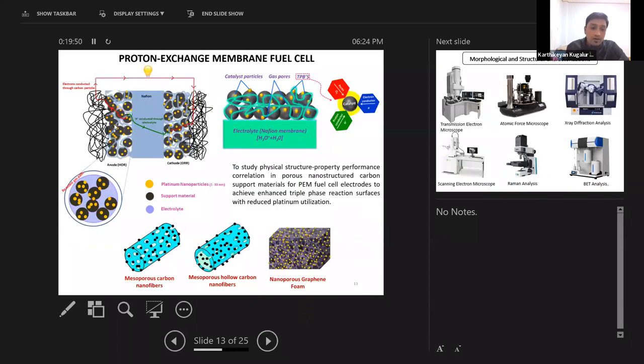But for the fuel cell purpose, instead of using the nanoparticle, we need to use the fiber form for increasing the specific surface area and increasing the porosity. And there are so many advantages for increasing the conductivity. We need to produce the carbon material in the form of nanofibers because it has several advantages over the particles. So we need to produce these nanofibers using the electrospinning method. But basically, the electrospinning method will produce only the polymeric nanofibers. When you treat with thermal treatment, the thermal treatment will convert the polymeric nanofibers into carbon nanofibers.